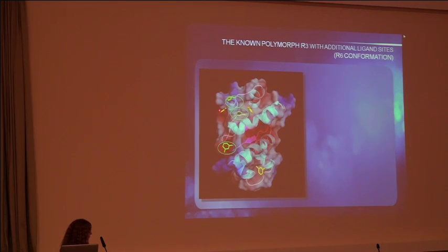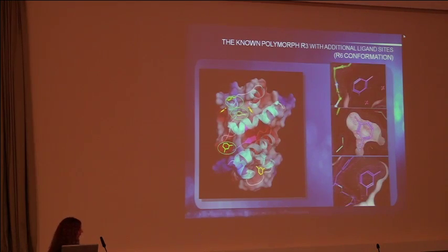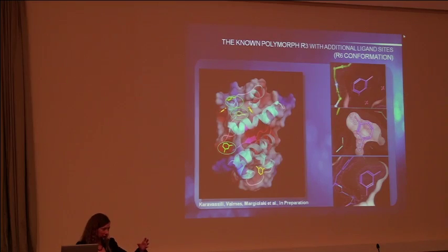From the literature, we knew that there are 3 phenol pockets on the insulin monomer surface, and we identified 3 more, each shown in green, and here are the 3 new ligand sites together with a portion from the total omit maps. This is very important for the pharma industry because most of the experiments pharmaceutical R&Ds are interested in are not to refine new protein structures, but to identify how a small organic, which is the drug, binds on the protein surface and how this affects its function. So now we can demonstrate that even this ligand identification might be possible with good quality powder diffraction data.